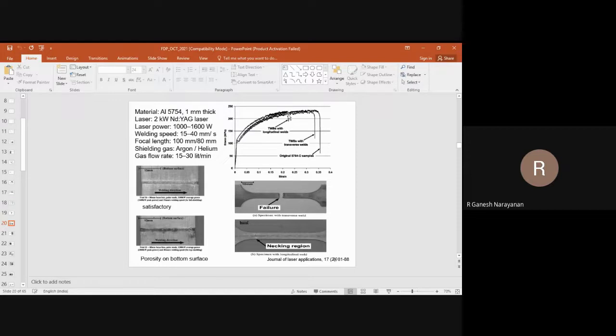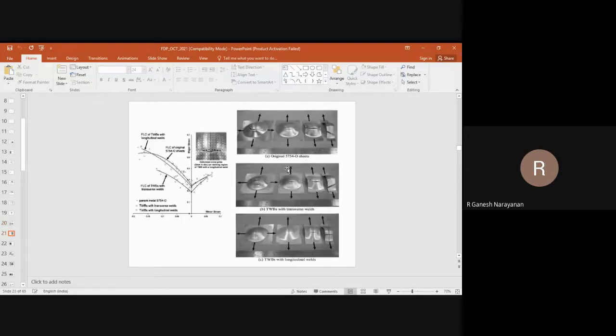Now you will see from a strength point of view, from let us say UTS point of view and yield strength point of view, all of them have almost the same. Yield strength you can see is about 120 megapascal, and UTS about let us say 225 or 230, close to that. But ductility, huge difference. Here it is 35%, here it is about 32, and here it is very low, about 22%.